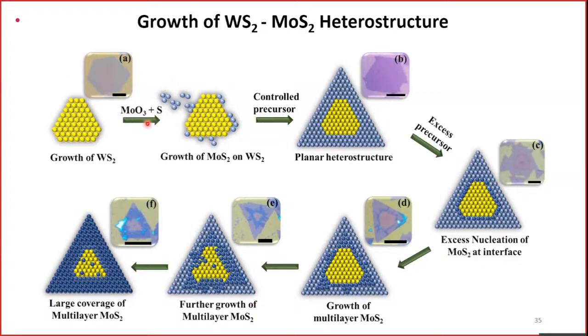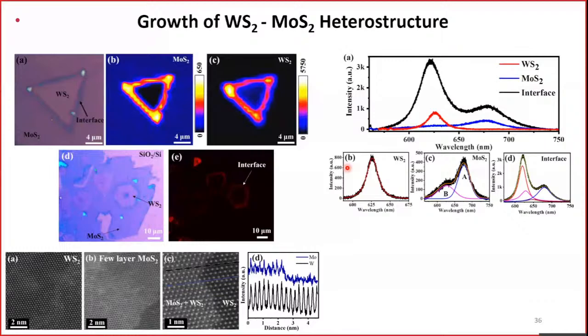It is also possible to introduce heterostructure formation in the CVD. It is very simple. First you finish the WS2 growth. After that, do the regrowth; you essentially introduce the MoS2 growth. Because of the edges already present, and WS2 and MoS2 have almost identical lattice parameters, we can get planar heterostructures. Earlier planar heterostructures were chemically the same, only the structure was changing. But in this case, it is chemically also different. This is WS2, outside is MoS2. Again, we characterized it in order to show that.